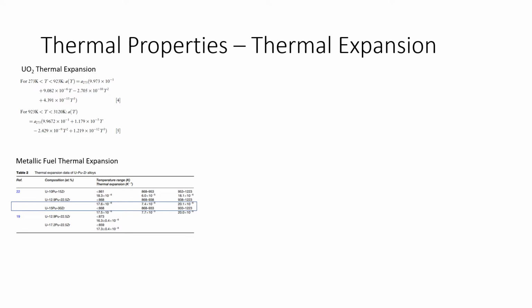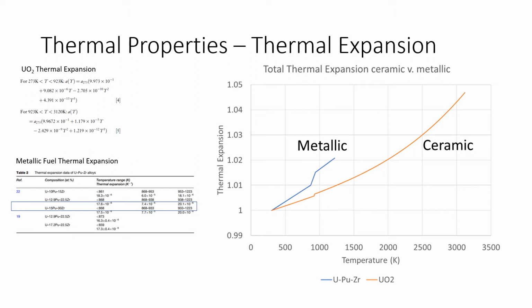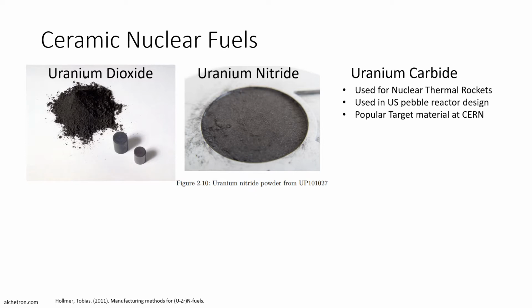Another piece of the thermal behavior is the thermal expansion. Shown here are 2 equations for the thermal expansion between ceramic and metallic fuels. I took the liberty and plotted them against each other. 2 things to note. Metallic fuels have a greater expansion rate. However, ceramic fuels have a greater total expansion in higher temperatures. Combined with a lack of thermal conductivity, the fuel experiences significant thermal stress on top of the other stress induced inside the fuel itself. This can cause unwanted pellet cladding interactions discussed later.